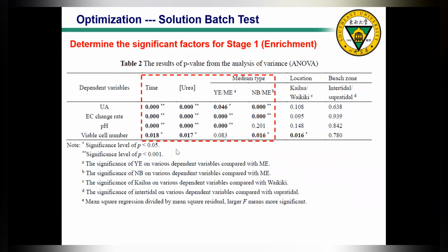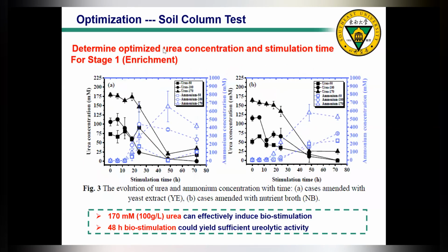Then, in order to further determine the optimized urea concentration and stimulation time, we did the soil column test. It's quite similar to the solution batch test. The only difference is that we directly inject the enrichment solution into the soil column, and after a certain period, we take soil samples and measure the urea concentration and ammonia concentration. So here are the results.